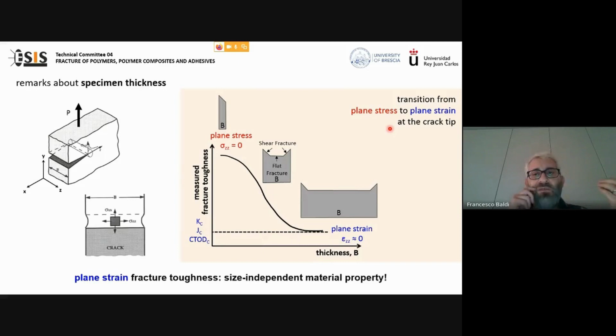Of course, also with polymers, we have the transition from plane stress to plane strain at the crack tip, with plane strain fracture toughness being the size-independent material property. Just to underline the fact that in polymers, if we compare the behavior of a given material characterized by a very low thickness with the behavior of the same material in a part characterized by very high thickness, we must remember the structure of the materials in the two different products. On one hand, a product characterized by very low thickness, and on the other, a very thick specimen, are different. This adds another degree of complexity to the analysis of the specimen thickness effects on the fracture response of polymeric material. Now I have finished my first part, and I invite Alicia to continue. Thank you for your attention.